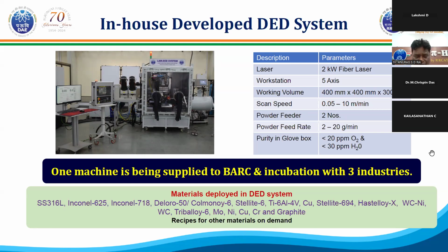Similarly, we have developed an in-house directed energy deposition machine, and one machine we are already extending into BARC, and we have given this technology to 3 industries. It is a 2 kilowatt fiber laser based machine with 5-axis workstation, having a volume of 400 millimeter by 400 millimeter by 300 millimeters. It has 2 powder feeders, so that you can use 2 metal powders simultaneously, change their compositions and work on it.